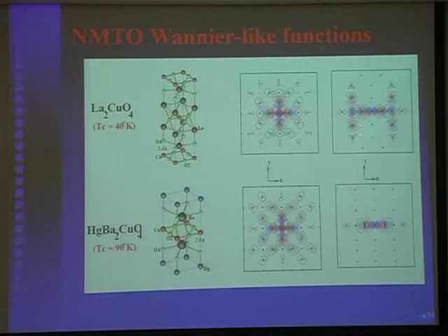So that means it builds up a linear combination of copper 3z², apical oxygen pz, and the lanthanum and copper s, which basically makes this blue lobe much fatter compared to the red lobe. That is copper s character, which is diffused, so you don't see it that well, but its signature you do see: it becomes much fatter.